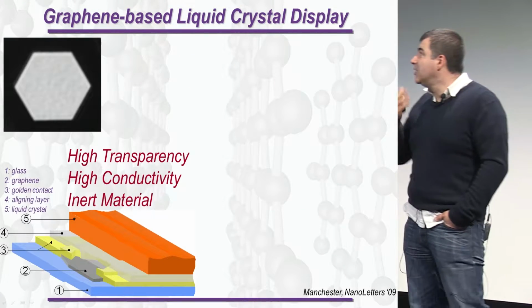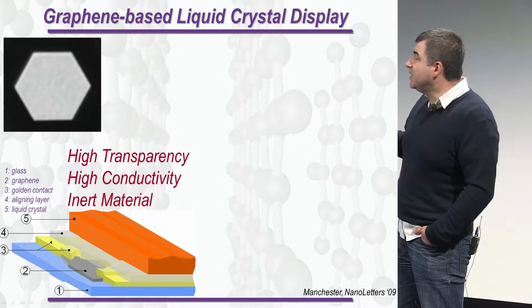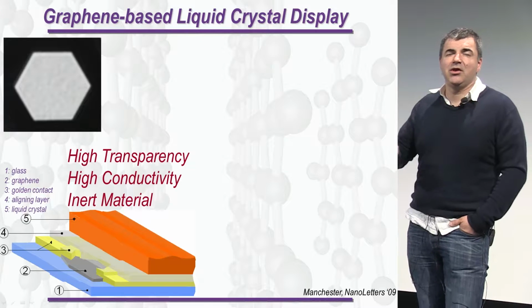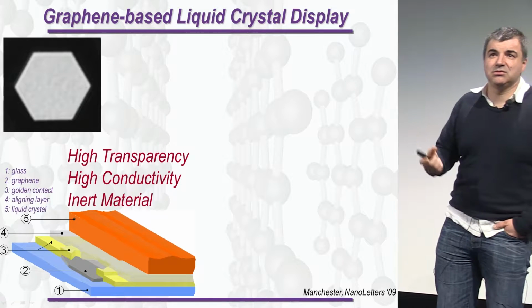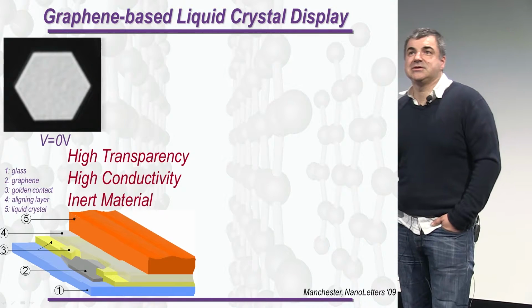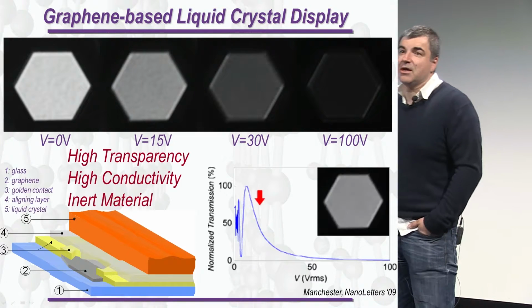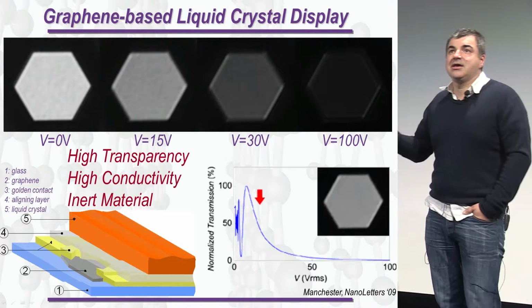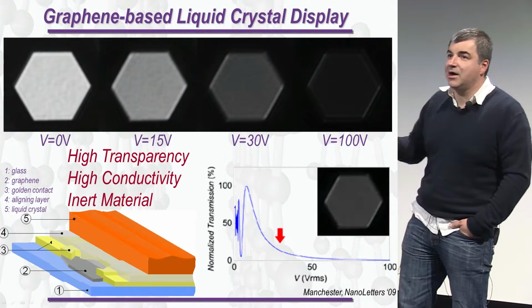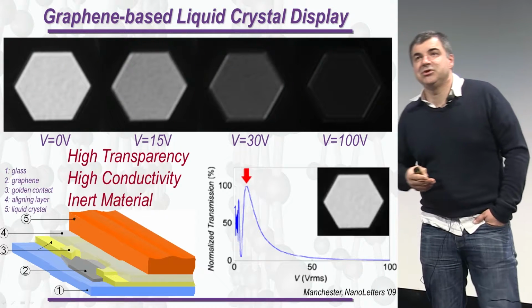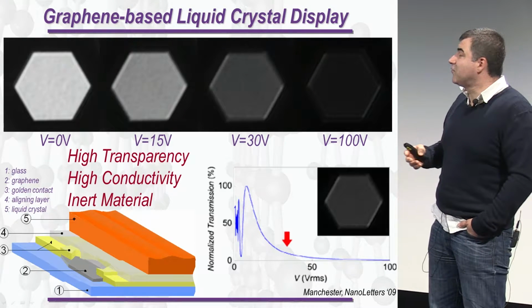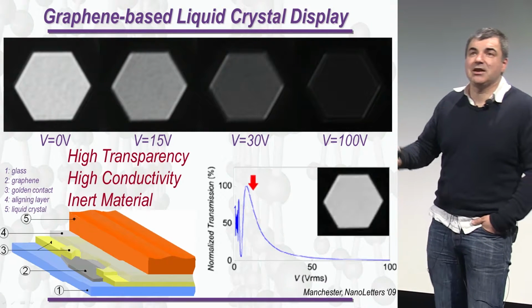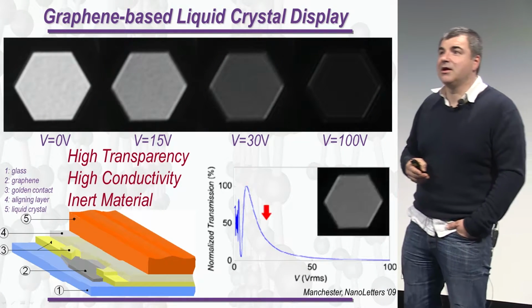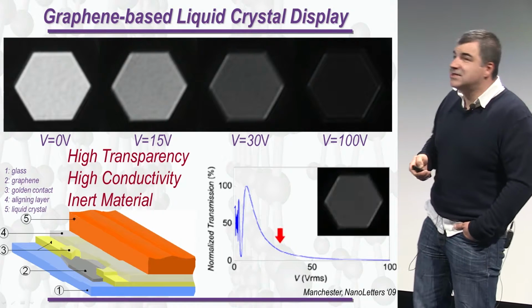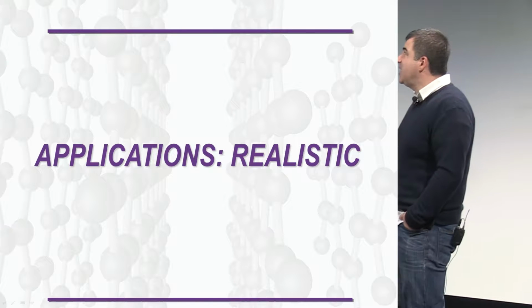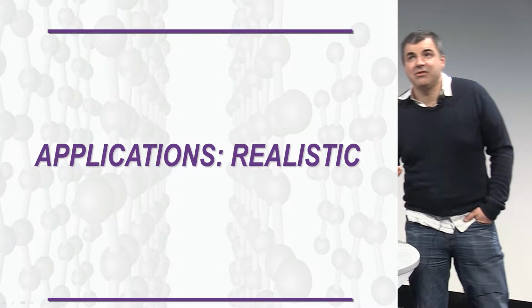And here is an example of a liquid crystal device like this, where we replace the traditionally used material, indium tin oxide, with graphene, and it does pinch off the optical transmission completely, so it operates well. And here we benefit not only from the high conductivity and good optical transmission, but also from the fact that it's flexible, mechanically strong, and chemically inert as well. And this tells us that probably applications with graphene should be quite realistic.